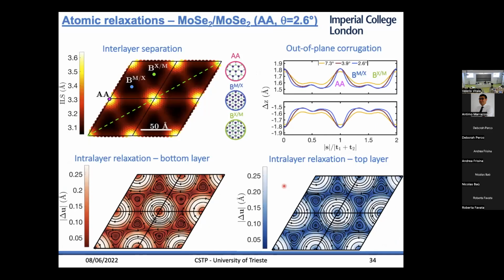Right. So relaxation. These are relaxations that we obtained with the classical force field, and the relaxation of the system is quite intuitive, because basically where the stacking is AA, the two layers tend to be far apart. And where the stacking is Bernal-like, the layers tend to be closer to each other, right? So this is the out-of-plane modulation along this diagonal of the Moiré cell.